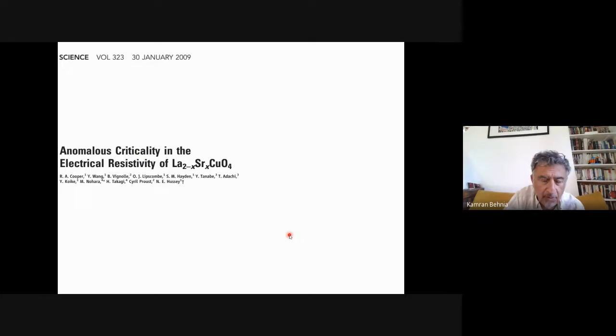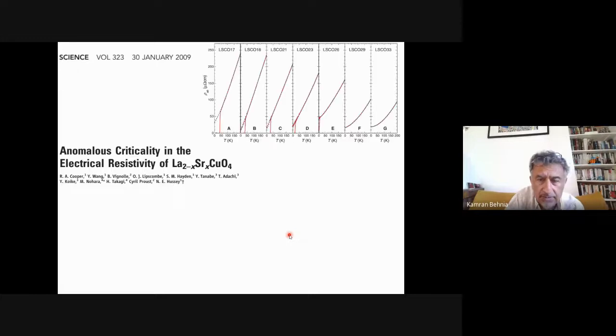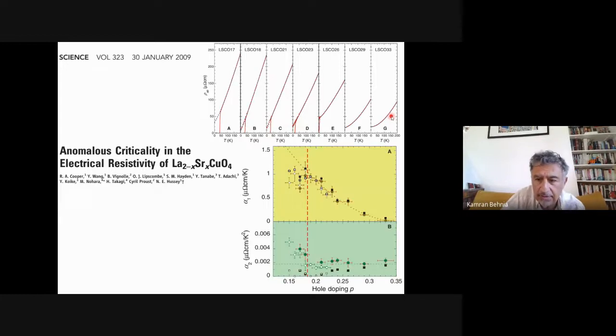Now, I would like to begin by mentioning an old work by my friend Nigel Hussey. So what Nigel and collaborators did was that they showed that actually, if you look at the evolution of resistivity in this system, when you are at 33%, where the system is no more a superconductor, resistivity can be fitted by a T-square term. So this is alpha 2 here. And there is no actually T-linear term. As soon as you become superconductor here, there is a finite T-linear term. The magnitude of the T-square term doesn't change that much.